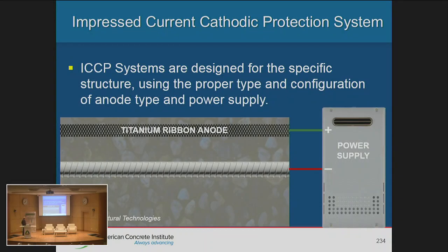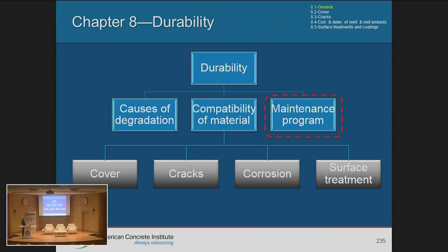That is the top of the line when it comes to corrosion protection. It's called the ICCP system, or Impressed Current Cathodic Protection System, where you have this titanium ribbon anode embedded into concrete, and an external power supply. The bars are connected to that power supply, and so is the titanium ribbon anode. So when the bar loses energy, it's supplemented by the power supply, which protects the bar from further corrosion by providing additional energy.